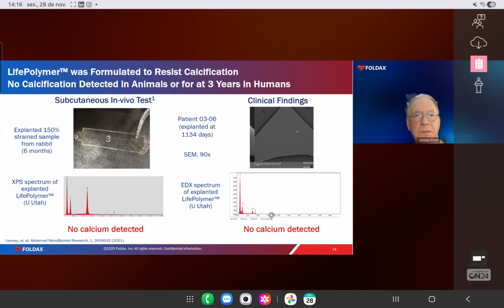for 6 months. And we compared, you can't see it here, but we compared positive and negative controls to life polymer. The positive control was the material that we knew would degrade in the rabbit in a very short period of time, in 6 months. The other material was a commercial material that's used by Medtronic as a pacing lead, very successfully in the pacing lead, but even that was damaged a little bit in the 6-month time period.